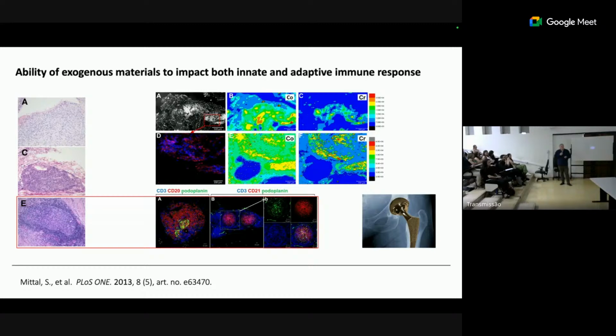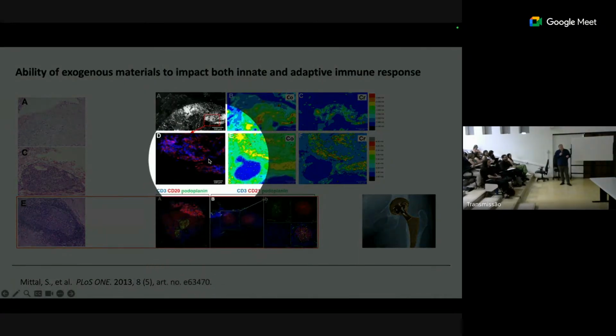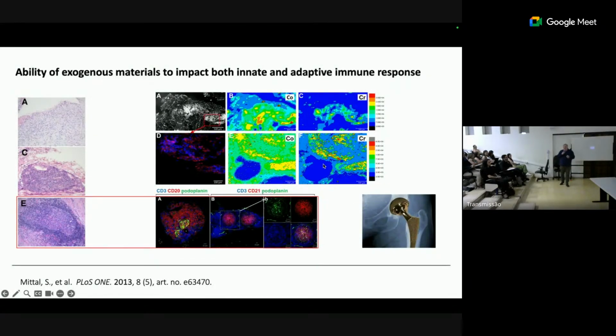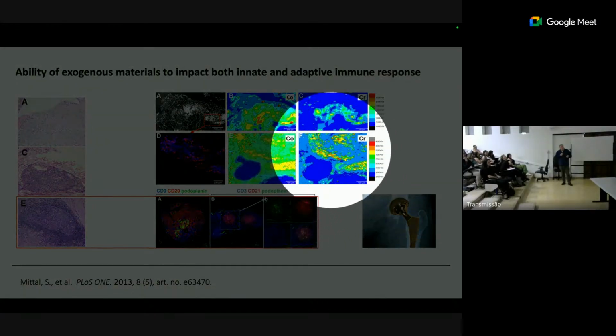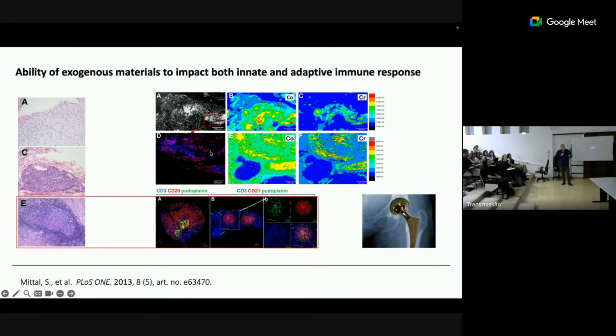And so what we did for that team was to take some tissue, initially working at quite low resolution, but then starting to map some of these tertiary lymphoid organs and then overlay metallic responses. Again, using a synchrotron, something that allows us to get a probe down to 1 or 2 microns in size and allows us to look at very, very dilute concentrations of metal. And we demonstrated that you had this high correlation, particularly with the chromium signal, which was being ignored at the time, with our T and B cell infiltrate. And that's over a decade ago.